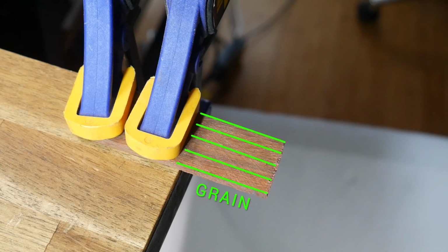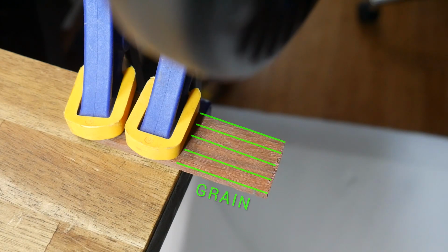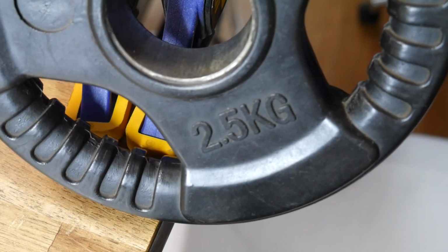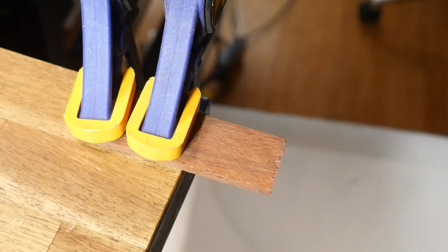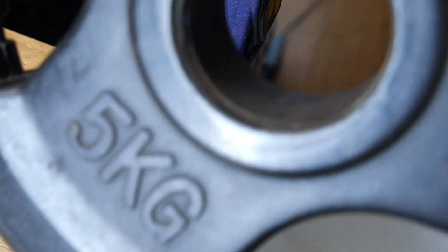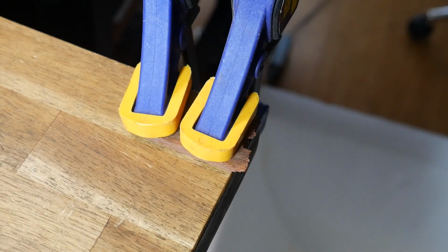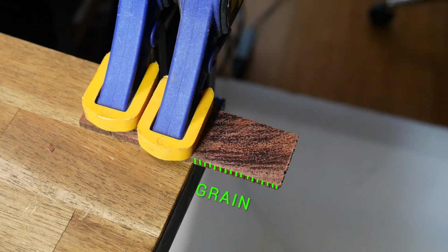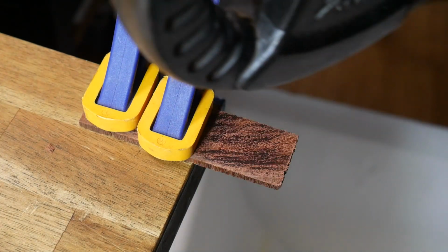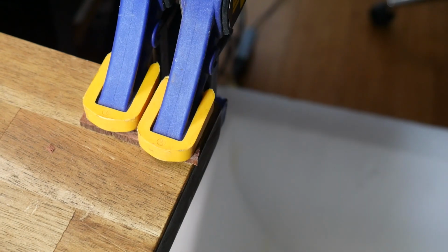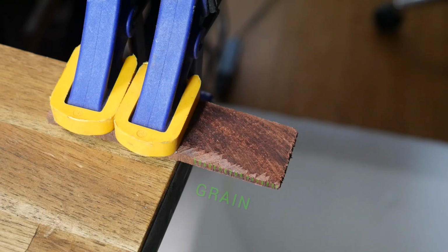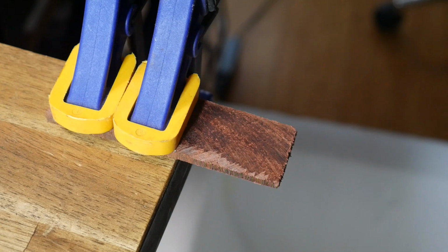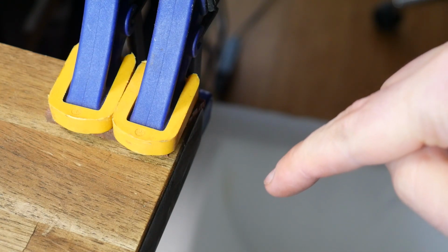Let's start by testing the timber where the grain is running along the piece, and as you can see, a 2.5 kilogram weight has pretty much no effect. We need to upgrade to a 5 kilogram plate before we get a result. So what about our cross-cut piece where instead we're attacking the end grain? Well, as you can see, the 2.5 kilogram weight destroys it. In fact, we don't even need any weight. Our finger is sufficient to easily break it in half.